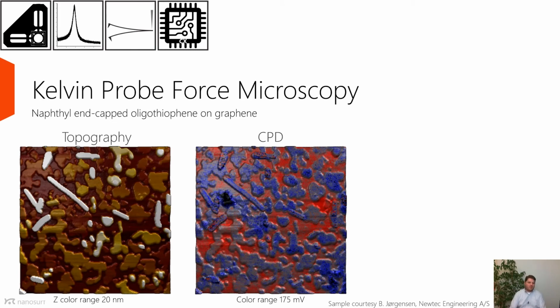One of them is the Kelvin probe force microscopy, which gives you some information about the contact potential difference of your materials. So what you see here on the left-hand side is the topography image of this naphthyl end-capped oligothiophene, which is basically adsorbed on graphene. And you can see there's different islands of different height. There's these rod-like structures. And with the Kelvin probe force microscopy, we can see that there is contact potential difference between, for example, this island here and that island over there, which can give you some idea on the arrangement of these oligothiophene molecules in these islands.